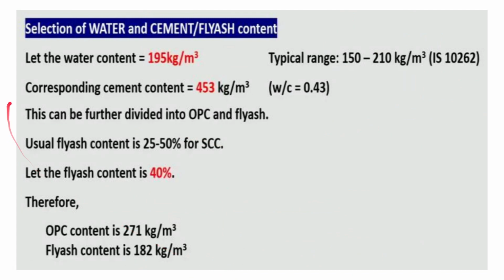Now, let us assume that our water content is 195 kg per meter cube, because it has been mentioned that it should be between 150 to 210 in case of SCC. So let us assume it to be 195. Using water cement ratio of 0.43, the corresponding cement content comes to be 453. They have assumed the water content to be 195 and taken the water cement ratio as 0.43, so the corresponding cement content comes to be 453.